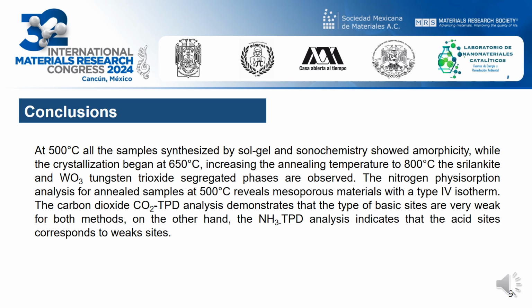At 500 degrees, all the samples synthesized by sol-gel and sonochemistry showed amorphicity, while crystallization began at 650 degrees. Increasing the annealing temperature to 800 degrees, the srilankite and tungsten trioxide segregated phases are observed. The nitrogen physisorption analysis for samples annealed at 500 degrees reveals mesoporous materials with a type 4 isotherm, and the carbon dioxide TPD analysis demonstrates that the basic sites are very weak for both methods. On the other hand, the ammonia TPD analysis indicates that the acid sites correspond to weak sites.